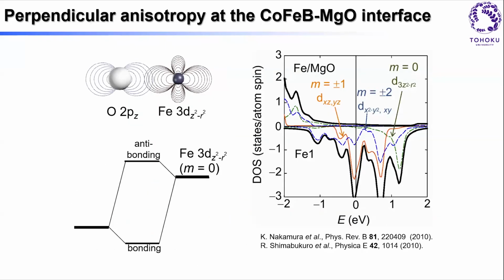Okay. The reason why there's such a perpendicular anisotropy at the interface is, for example, iron has 3d orbitals. They have crystalline anisotropy, and they're almost all fully compensated. But bringing oxygen to iron, one of the d orbitals bonds to oxygen and is removed from the scene, which means that, since this has an in-plane anisotropy, from the compensated structure we subtract the in-plane anisotropy and get perpendicular anisotropy. That's how we understand this.